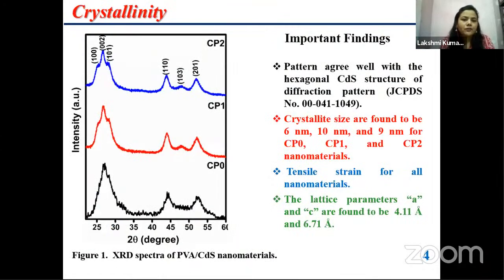After preparing the powder form, we have studied its crystallinity property, and from XRD we can see here that the crystallinity increases with capping of PVA in CdS, and also these XRD patterns agree well with hexagonal CdS nanostructure. The CdS structure diffraction peaks are mentioned here, and crystallite sizes are found to be 16 and 9 nm for pure and capped systems, and all have tensile strain, and lattice parameters have also been calculated, which are mentioned here.